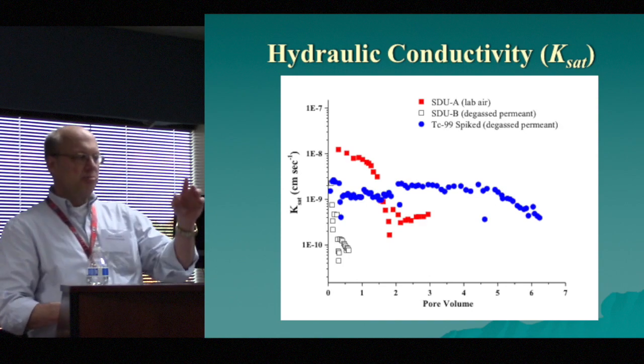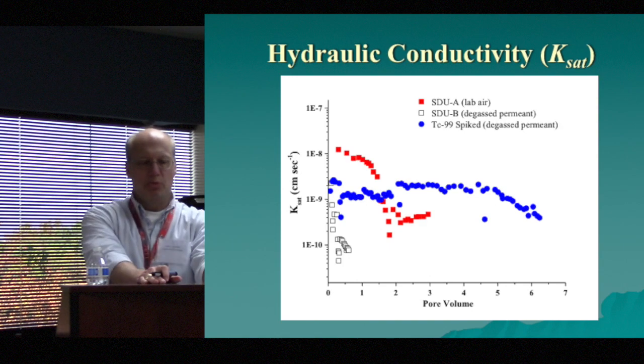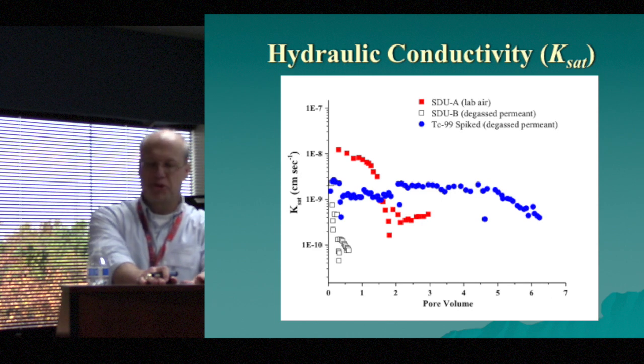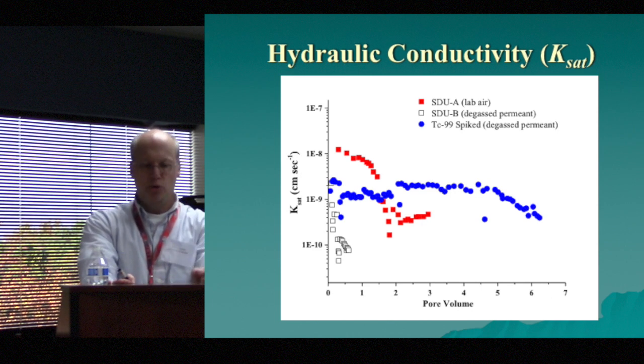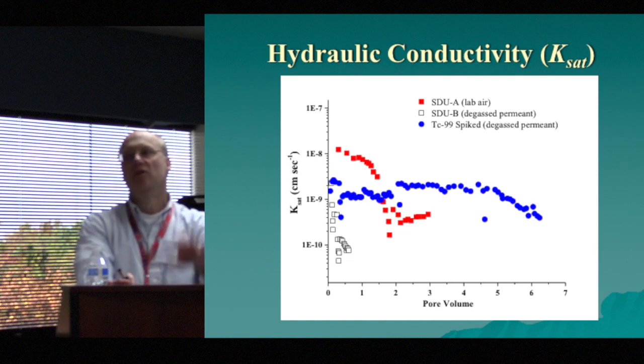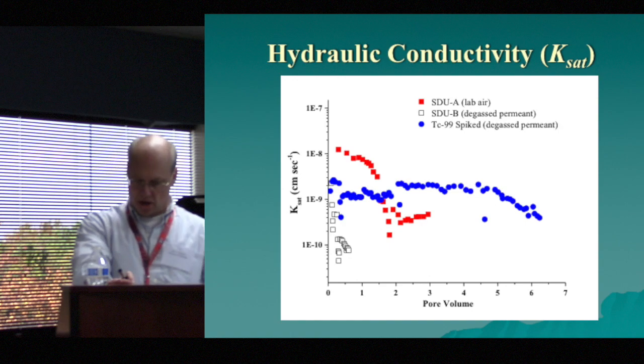I didn't touch on this, but when you're doing this system, you have an inlet pressure, you have a flow rate at the outlet, and you have known dimensions of your sample, so you can always calculate the hydraulic conductivity of this material as you go through the experiment. Next.